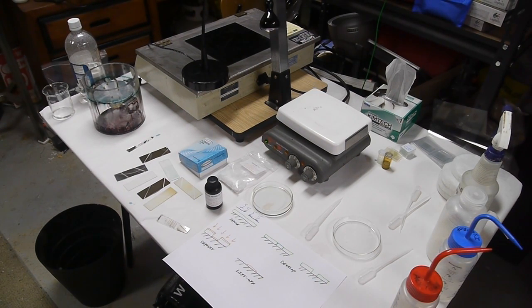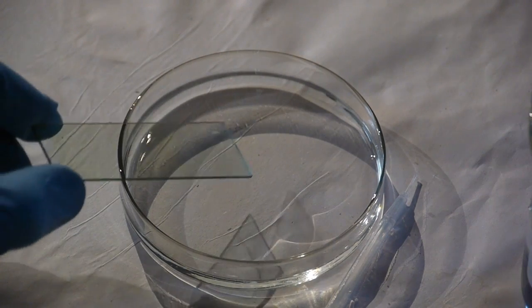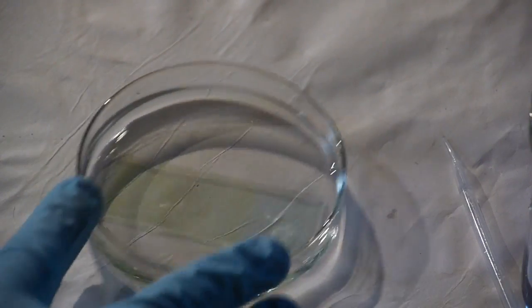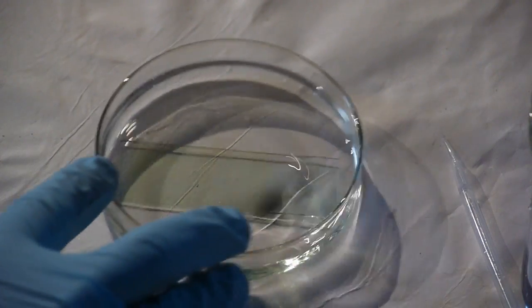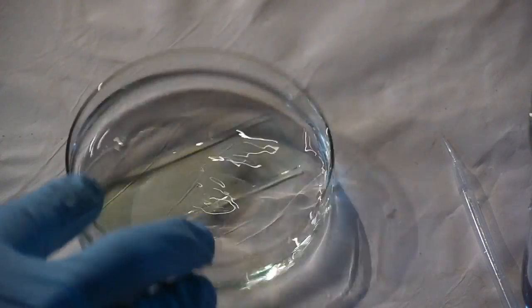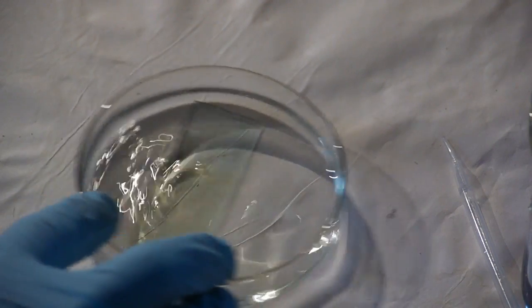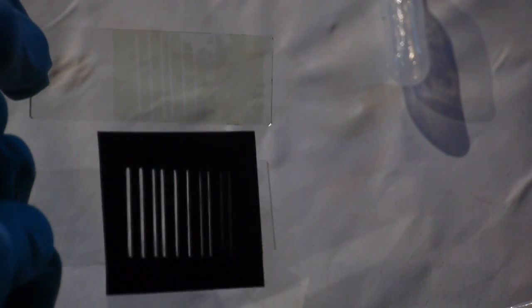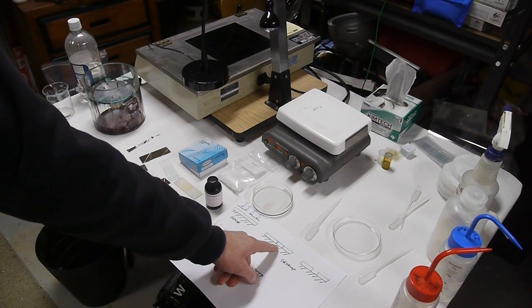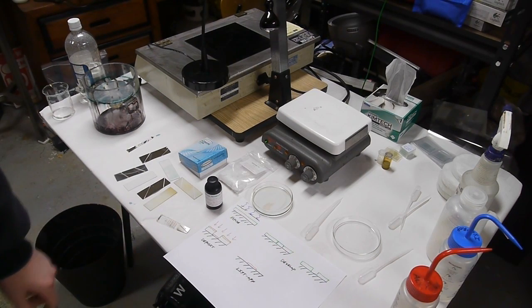These are not the best things to use. I'm trying to get some sodium metasilicate, which is a much more forgiving developer. The problem with sodium hydroxide is that it goes from underdeveloped to overdeveloped very quickly. Mike's Electric Stuff helpfully pointed out that sodium metasilicate pentahydrate is a much better choice. I've got some of that on order. After the developing process, we've got the patterned photoresist, and the developer has removed it where the photoresist was exposed to UV light.